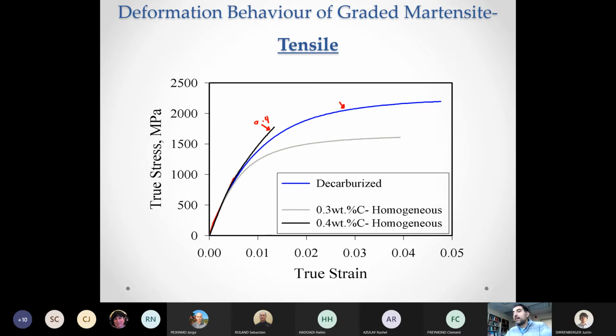that sample. And just for the comparison, I also put the sample with 0.3 carbon. And you could see that the decarburized sample is better than both in terms of strength and ductility. So we can achieve properties in the decarburized material that are superior to what we can get in a homogeneous material.